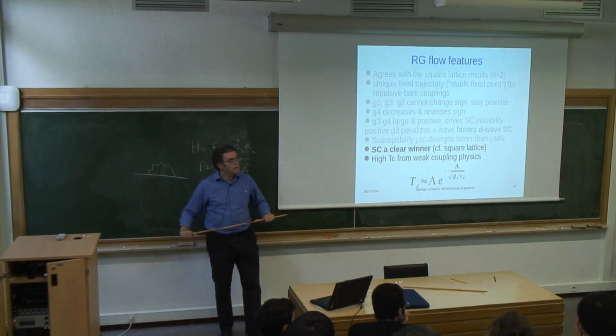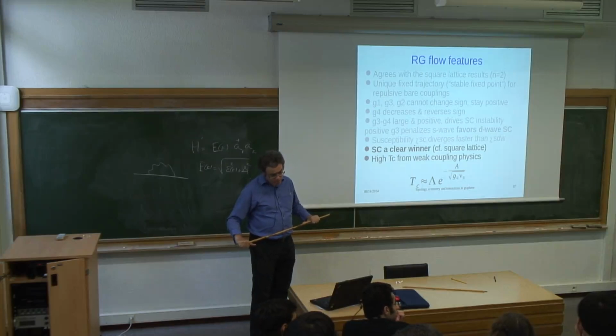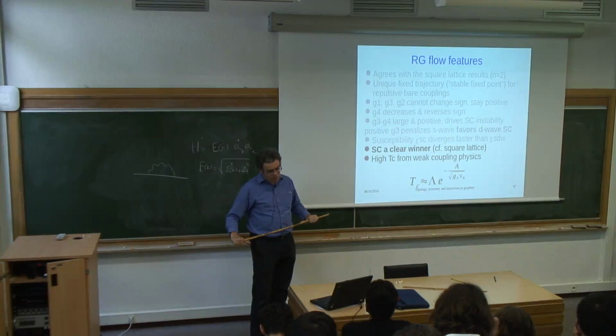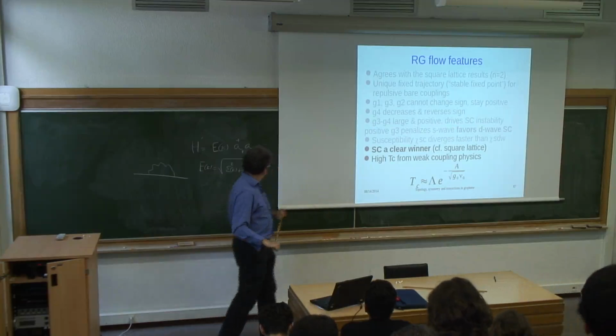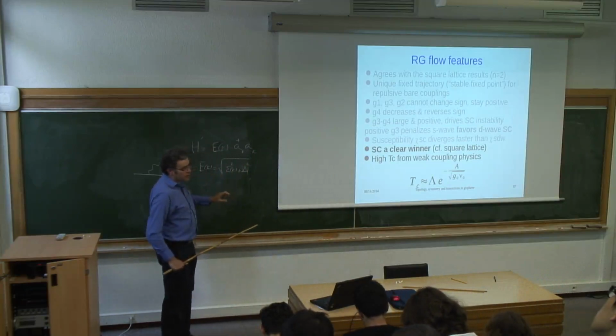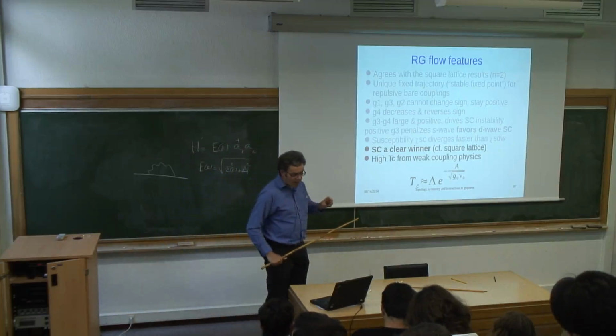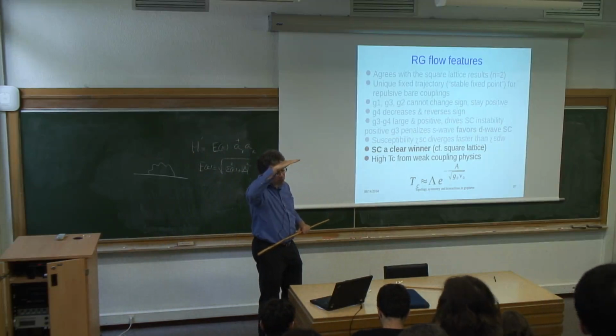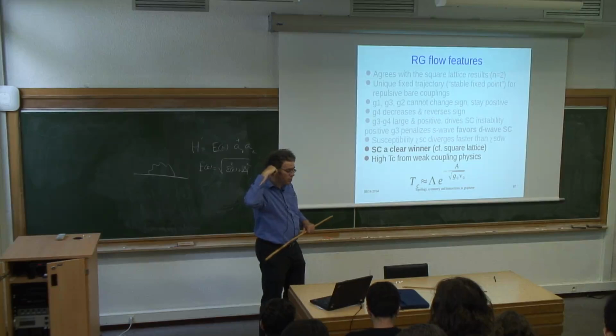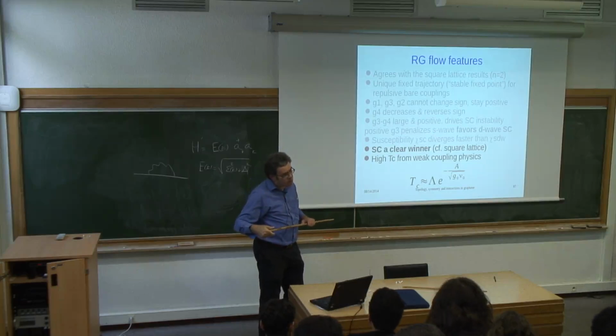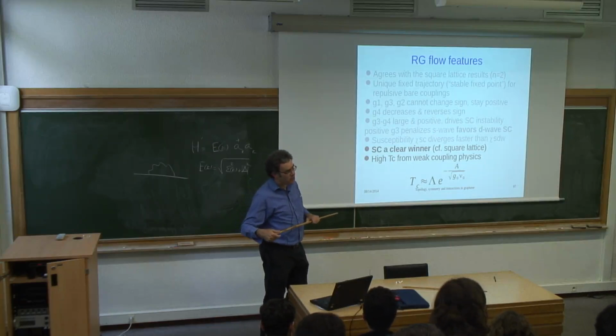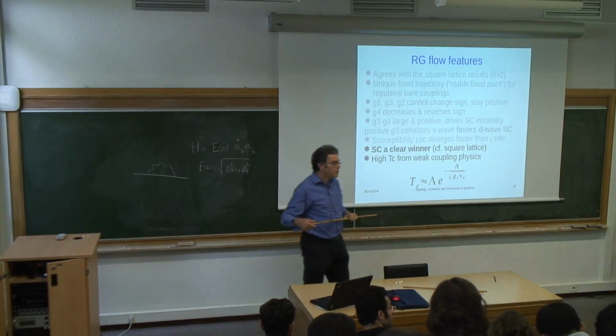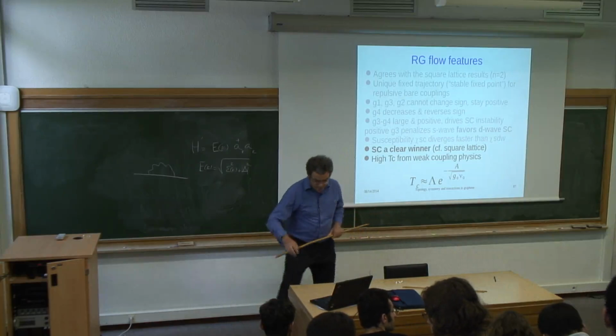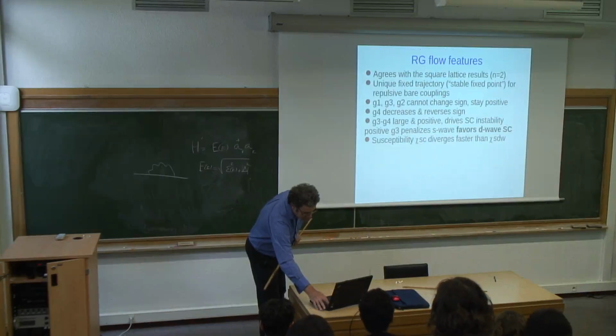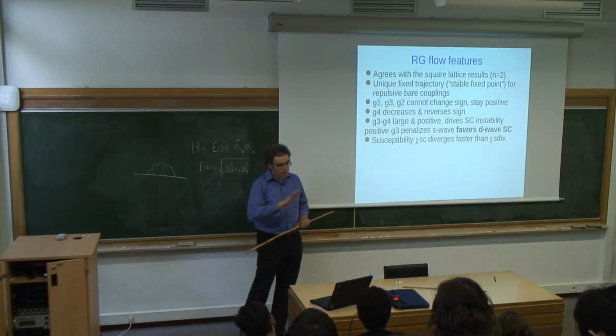Any other questions? Is this for long-range Coulomb or for Hubbard-like repulsion? No, so this was for short range. So you start with repulsion, but then you project it on states near the Fermi surface, and when you do that, your wave number is of order k Fermi, but k Fermi for this Fermi level, which is somewhere near the saddle points, is of order of graphene lattice constants. So essentially it's Hubbard. But then what makes it qualitatively different from a square lattice? Because in a square lattice, if you do this, you get, somehow, the spin density wave that wins. That's right. So you have nesting and so it's similar. However,